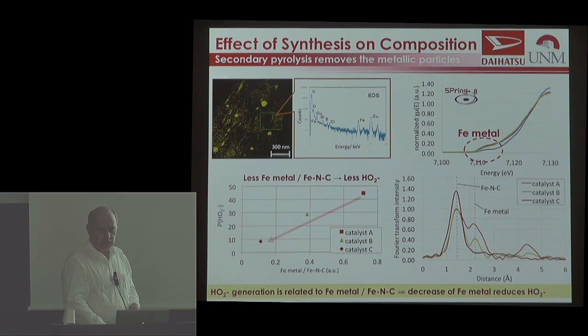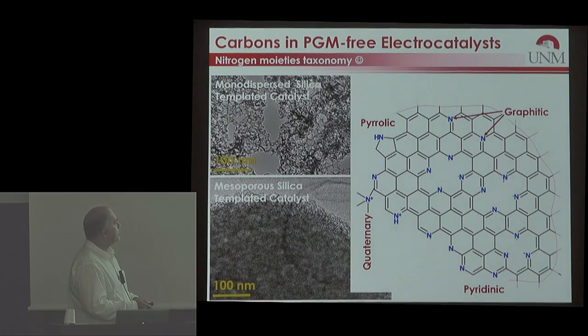So how do we think about the material? We think of the material as defects in a graphene sheet. These nitrogen defects can be around vacancies, a double vacancy or single vacancy, or they can be around the edge. Again, defects that are simple incorporation of nitrogen into the graphitic sheet are of no interest. They have zero reactivity in the oxygen reduction reaction. So only those that can coordinate the iron are of interest to us.